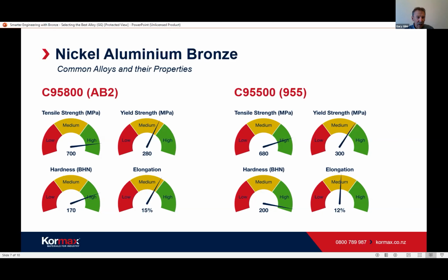And associated with the aluminium bronze, it's still an aluminium bronze, but we call it a nickel aluminium bronze. Now the previous aluminium bronze 954, I should have said, is typically just about 85% copper, 10% aluminium, 5% iron. With the nickel aluminium bronze, you add another 5% nickel to the mix. That makes it a slightly tougher material, but the thing it does do is improve the corrosion resistance. The 954 type material is not the best for corrosion, but it has good corrosion resistance, but it's a bit susceptible in harsh environments like seawater and things like that.